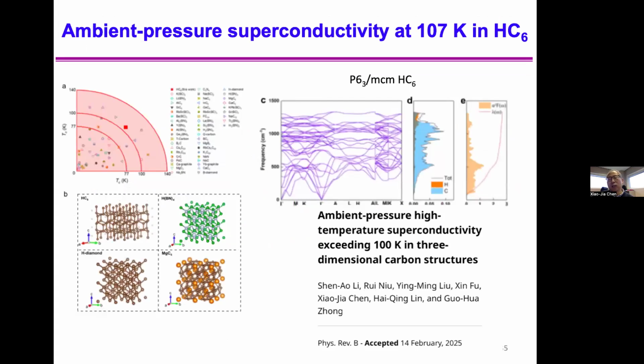Very recently, a few days ago, a paper was accepted by PRB. In this paper, we have just two elements, hydrogen and carbon. You can see hydrogen carbon 6. That's a TC above 100 Kelvin. This is actually realized at ambient pressure.